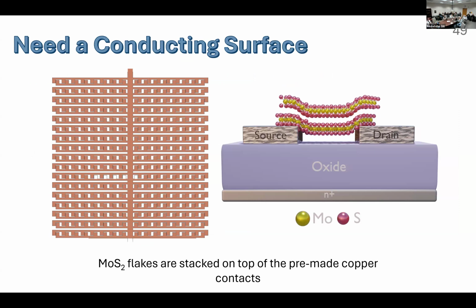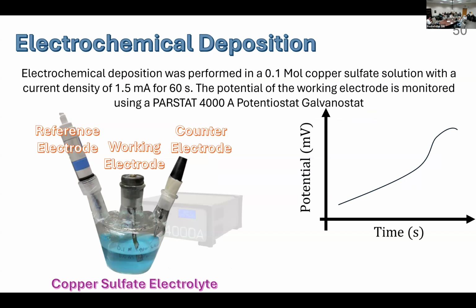So MoS2 flakes are exfoliated and, using a stamp, placed on top of these pre-made patterns, where the copper is expected to deposit on these sides. Doing that, we can actually go and perform our electrochemical deposition. We perform this in a 0.1 molar copper sulfate solution. This was done at a current density of 1.5 milliamps per centimeter squared for 60 seconds. The potential of the working electrode is monitored using a potentiostat.